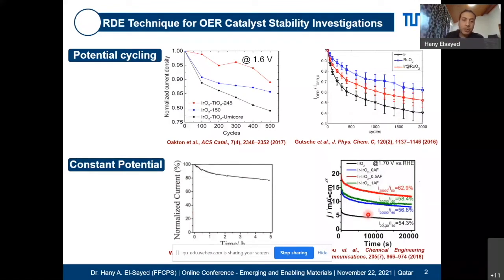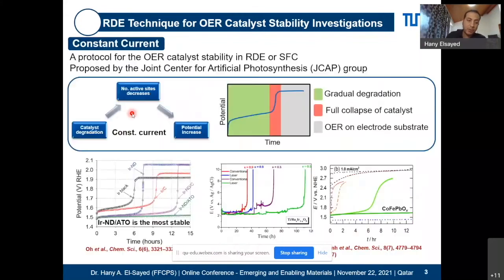Well, these are only two different methods. There's another method here, which is called the constant current. And this is, I would say, the dominating method in literature. A lot of people working in the electrolysis area know that in order to use something that is more relevant to the application, it is better to apply a constant current and monitor how the potential changes with time. This technique has been used in literature for the last 10 years. And what I'm going to show you is that, unfortunately, this method is not very reliable. But let me first explain exactly what is happening there.